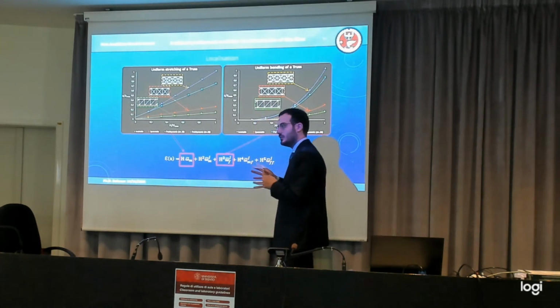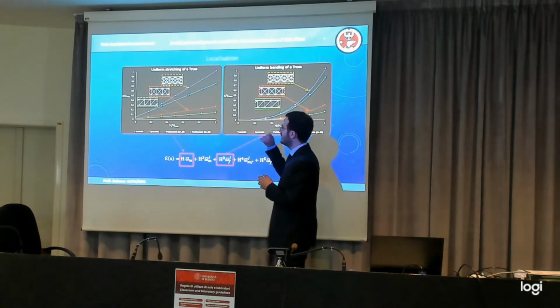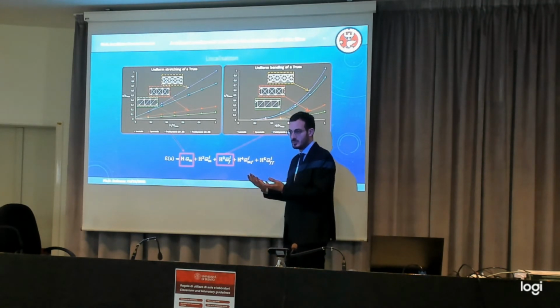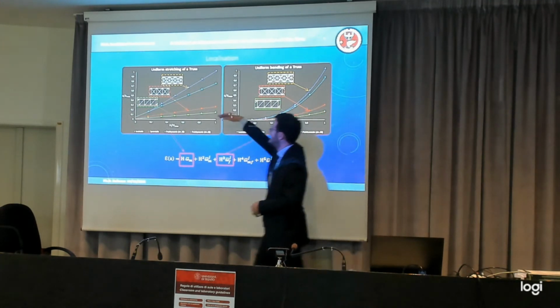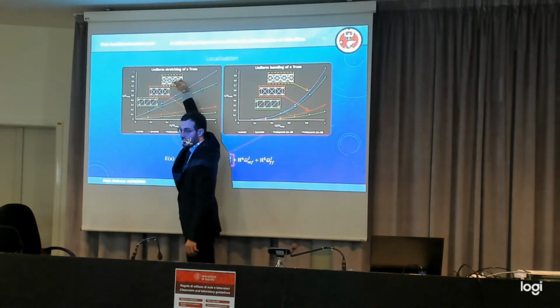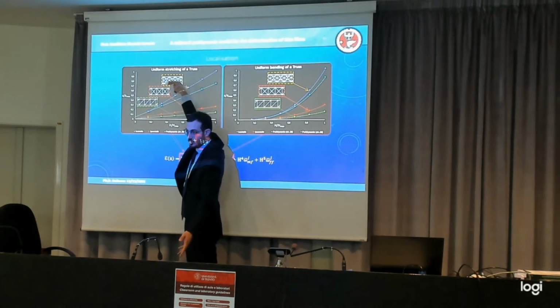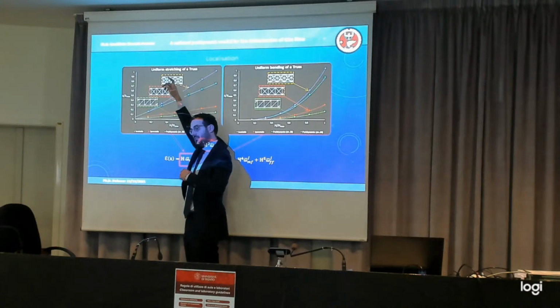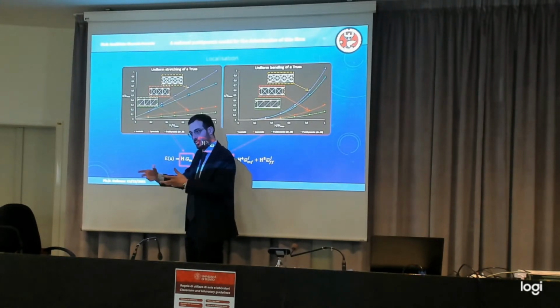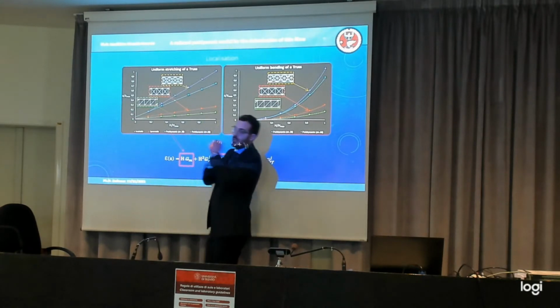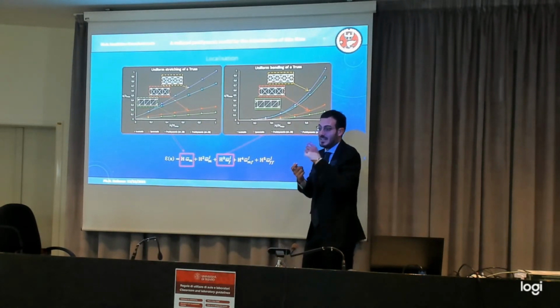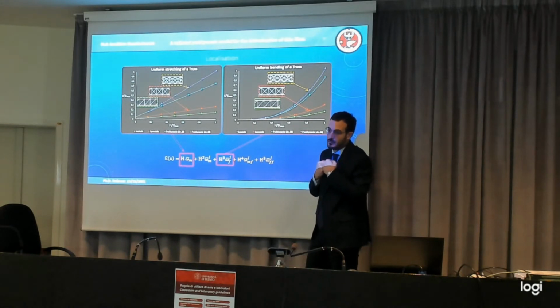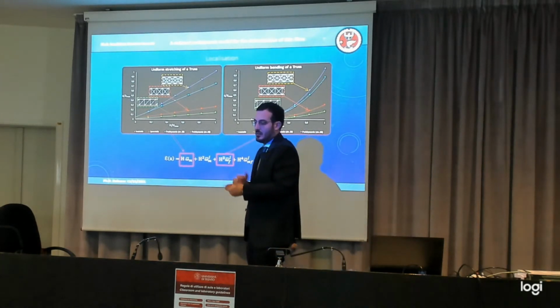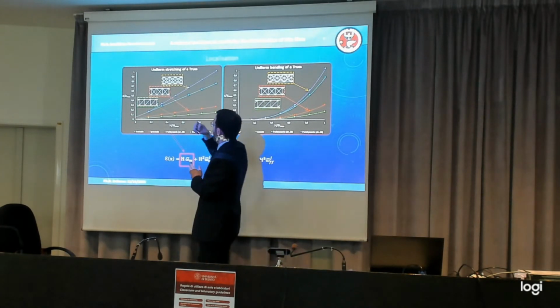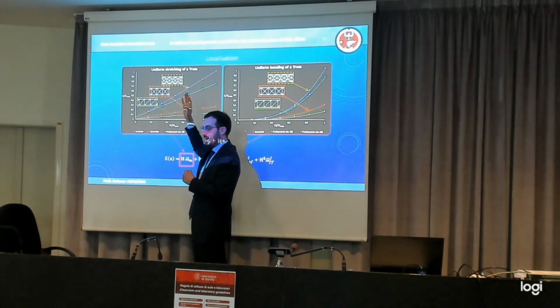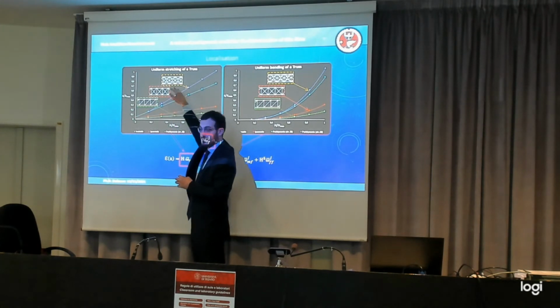Okay, so when you increase the discretization, you are increasing the number of bonds. Crack propagation in peridynamics means that you have to cut more bonds. The more bonds are cut, the more energy is stored. But since you want to keep the overall energy consumed by crack propagation the same, you need to reduce the critical elongation so that each bond can store a smaller amount of energy. This is just a direct consequence of the fact that numerical simulation explicitly requires a discretization through the thickness,